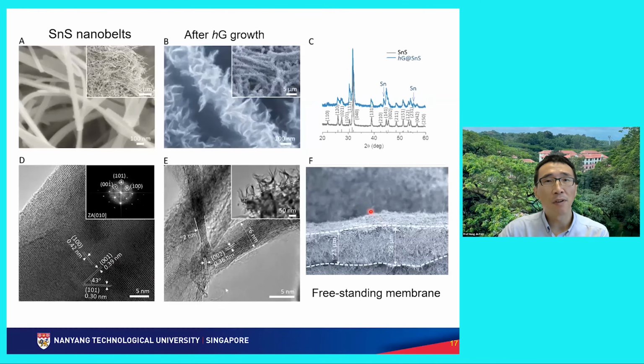Okay, so in this work, first we have these tin monosulfide nanobelts, like grass hairs. If you go to the barber's, you can see this hair-like structure. And after the growth of the hierarchical graphene surface by the plasma method, all individual nanobelts are covered with this hierarchical graphene. If you go to TEM, you can see it like this. This is the tin monosulfide. This is the graphene, layered structures. After the coating, the whole film is about 30 micron thick. Every surface is coated with this graphene surface. You can imagine that the whole surface becomes more conductive and stable.